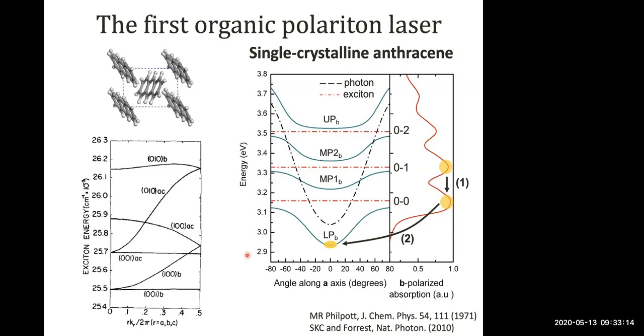One of the reasons anthracene was first studied was really because of this worry that localization in space somehow prevented polariton lasing. It turns out that's not the case, but it was a strong motivation for looking at single crystalline materials to realize condensates. And then condensation in this material happens when the lower polariton branch minimum is exactly one vibrational energy away from the reservoir, which is here at this 0-0 peak. So in the polariton spectra, we don't see anything here, but we know this is where the bare resonance lies.